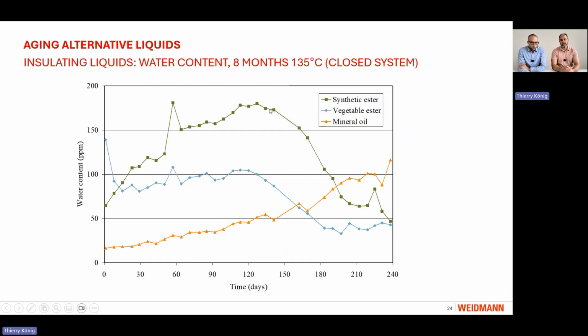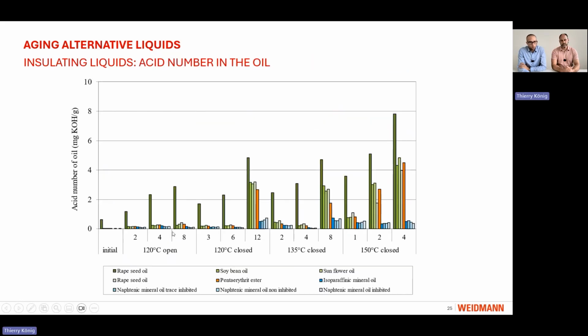So from this moment we have a decrease in the water content of these ester-based liquids, and in the mineral oil the water content is increasing over time. When you look at the acid number in the insulation liquids, we can see the open and closed system in comparison. In the open system, we can hardly see an impact. Only the one rapeseed oil has an increase, but it already has quite a higher value from the beginning.